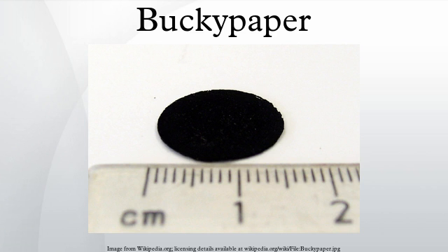Washing with methanol, an effective solvent in the removal of Triton X, was found to cause cracking and deformation of the film. It has also been found that Triton X can lead to cell lysis and in turn tissue inflammatory responses, even at low concentrations. In order to avoid adverse side effects from the possible presence of surfactants, an alternative casting process can be used, involving a frit compression method that did not require the use of surfactants or surface modification.